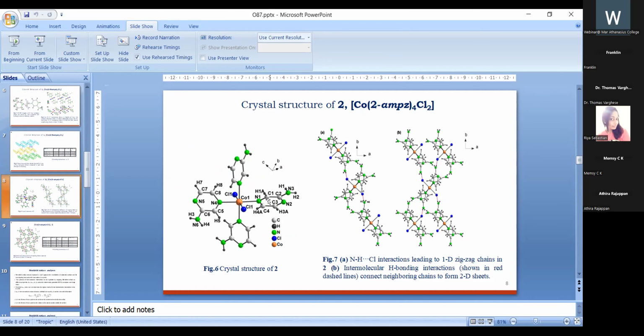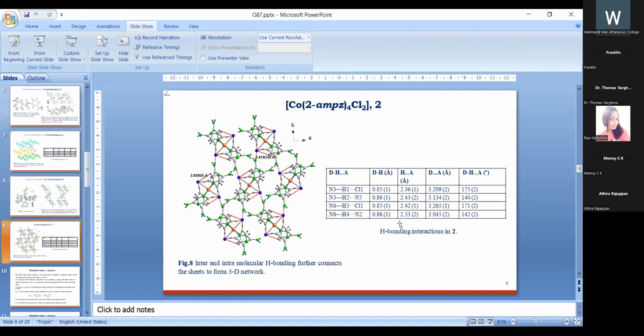And unlike in 1, here the aminopyrazine moieties are not protonated. In the structure of 2 also, there are extensive hydrogen bonding interactions, mainly N-H...Cl interactions, leading to one-dimensional zigzag chains, which are further connected to form two-dimensional sheets. Inter and intramolecular hydrogen bonding interactions further connect the sheets to form a three-dimensional network.